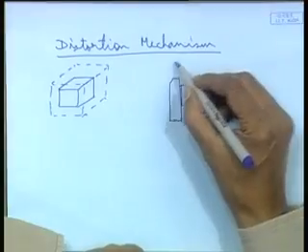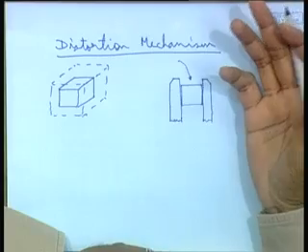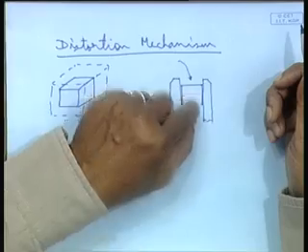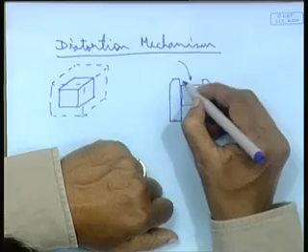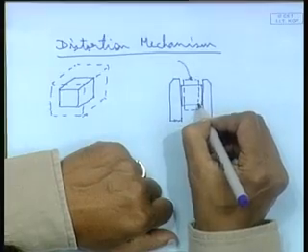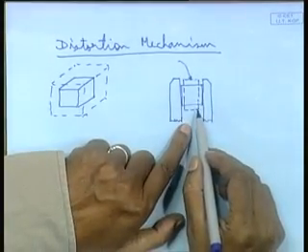And now suppose again you heat it uniformly by some means, say by a gas flame engulfing the entire cube, uniform heating. Here also I am heating it with a gas flame, right. Now supposing I am not measuring what is happening, I am heating it and letting it cool down, I will find that it falls off. After it cools down, the immediate observation would be that it is not holding to the place, it will fall off. And now if I measure, I will find the shape of the thing has become somewhat like this. What I am showing you in the dotted line is obviously a little exaggerated, but like this. That means it has become narrower in this direction and has increased in the other direction.